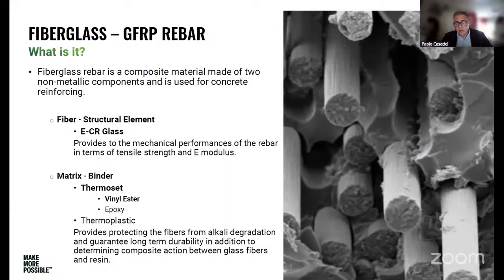The fibers provide the mechanical performance of the rebar in terms of tensile strength and Young modulus, whereas the resin protects the fibers from alkali degradation and guarantees long-term durability, in addition to creating the composite effect. Imagine having all these very fine spaghetti next to each other; the only way we can make them work together is through the resin. So the resin is really the load-bearing transfer between one fiber and the other.